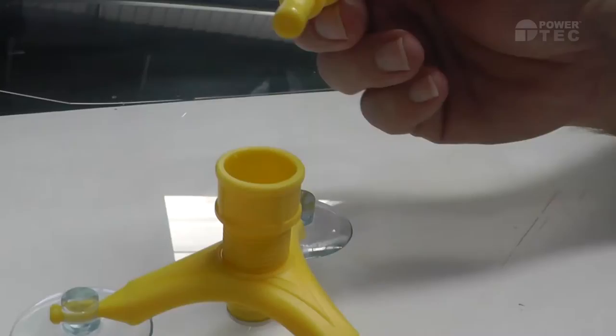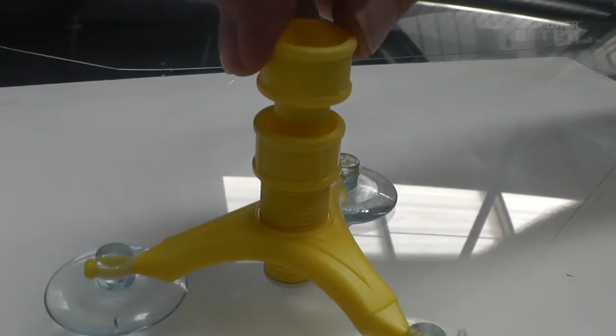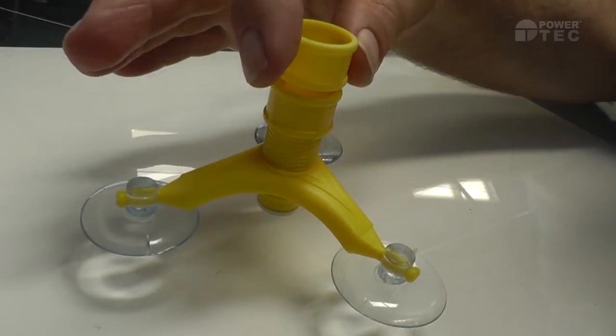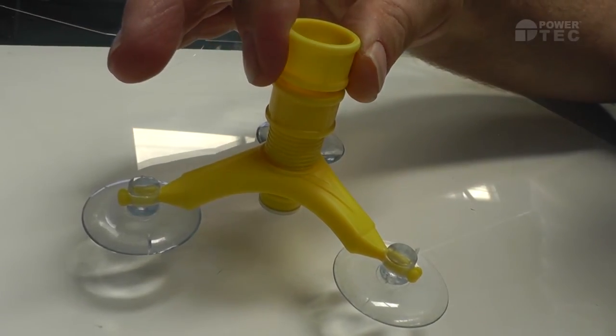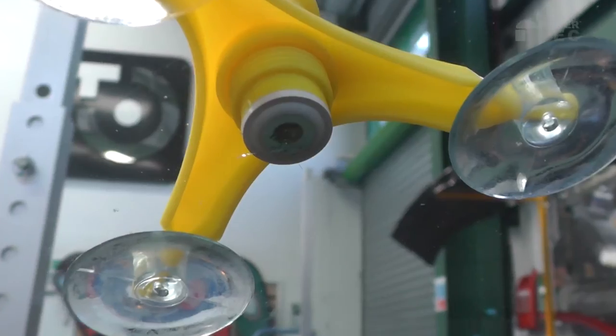Screw the pressure driver into the injector barrel and steadily turn until resistance is felt. It will begin to build up pressure, forcing the resin into the crack.